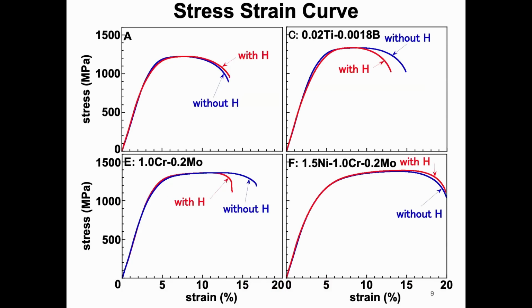This figure shows the nominal stress strain curves of steels A, C, E, and F. You can see that the stress strain response, such as yield strength, the maximum strength, and work hardening behavior, was hardly changed by the hydrogen absorption. In steels C and E, the fracture strain decreased significantly by the hydrogen charging. On the other hand, the fracture strain of steels A and F hardly changed by the hydrogen charging.